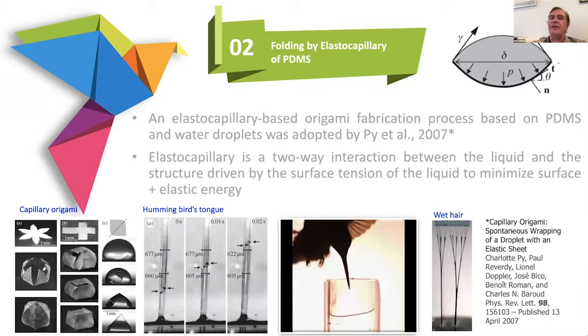So now we come to a first step in the evolution towards what we're going to be presenting today. And that is to do the folding of the paper, not by hand, but by elastocapillary. As I told you earlier, this was work first presented by Py et al. in 2007. The idea there is, let's say here you have a flower cut out with scissors out of PDMS, or here you have a T-shaped structure. If you now put a droplet of water onto this shape, it will self-assemble.